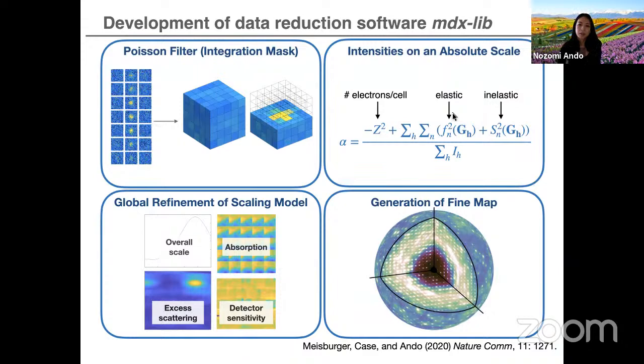And the other reason why this was important was because by placing intensities on an absolute scale, that meant any sort of model that we fit to it would also have to explain the intensities. And so it would allow for more rigorous tests of model data agreement. And what resulted from that was a very finely sampled three-dimensional diffuse map, which I'm showing here.